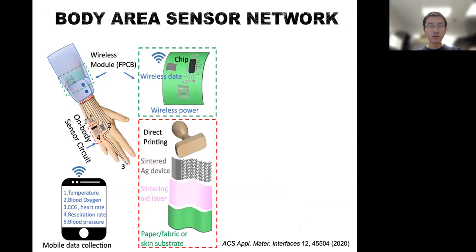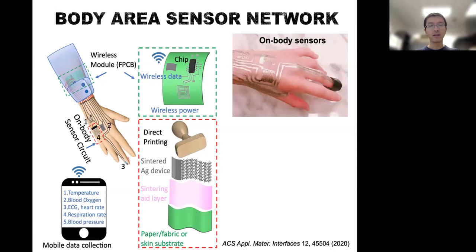And then moving on to some of the demonstration of the device level. From the single sensor, we can move on to the sensor network, so on different body areas, to help us build the body area sensor network. And from that perspective, we try to integrate the sensor with the wireless transmission unit. And the particular thing in this work is to have everything fabricated through a very simple manufacturing approach. And the material is all based on silver nanoparticle. And silver nanoparticle is very hard to sinter because the temperature will have to be over 300 to 400 degrees C. And here we use a sintering aid layer with different nanocomposite material inside.